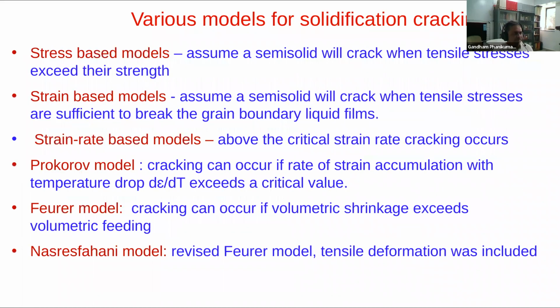One of the celebrated theories is by Lippold. I will not go through all of them; I just mention some names you must have heard of. Prokhorov's name is very popular in cracking, because anybody talking about hot cracking should mention Prokhorov's model, as it was one of the first successful models to explain the cracking tendencies. He said that by looking at the strain as a function of temperature, and whether it exceeds a critical value or not, one can comment upon crack formation or not, respectively.